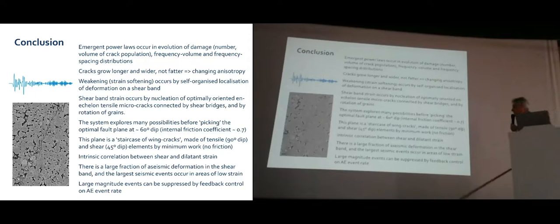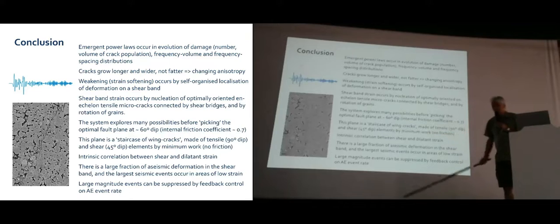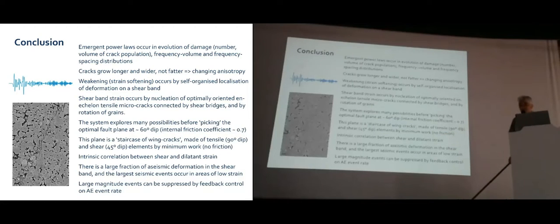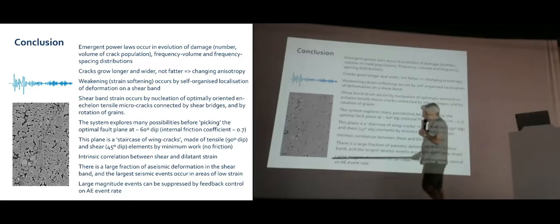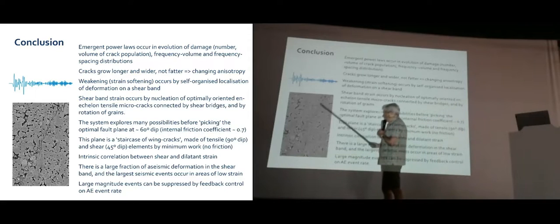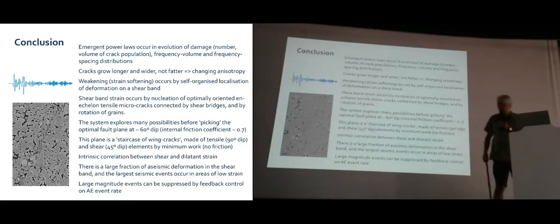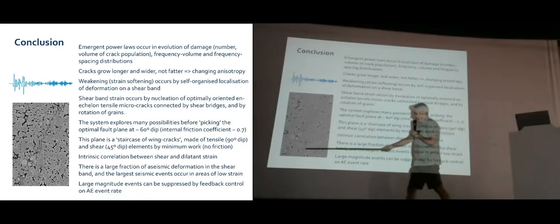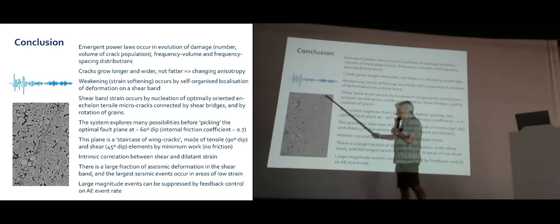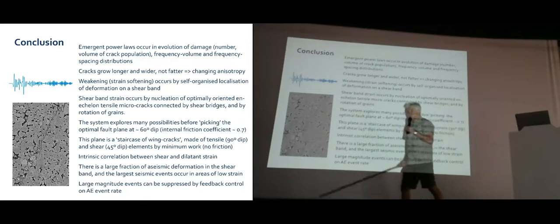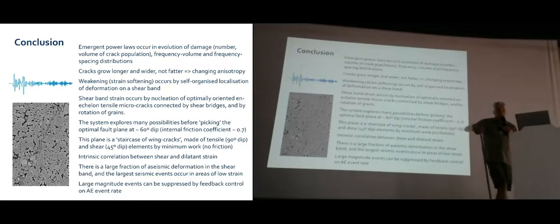And that's a bit of the magic of the emergence of faults in brittle materials. It happens very quickly. So the knowledge that this bit is broken has gone to the end of the sample very soon after peak stress, through the stress interaction between the elements. Even though there's not a fault there, the knowledge has been transferred very quickly.